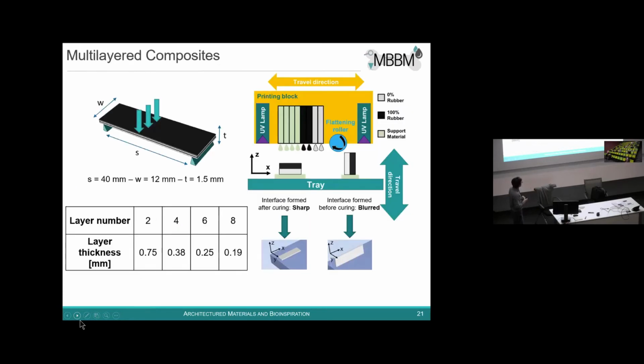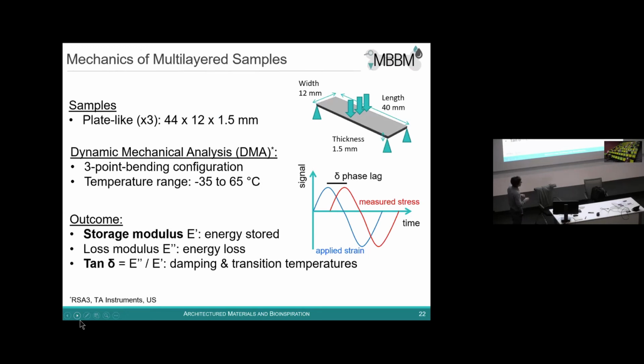And then we wanted to assess the impact of the interface on the behavior of very simple multi-layer composite materials. So we printed composite materials at the millimeter length scale of alternating layers of soft and hard polymers. And we printed them such that the interface between the different layers was sharp or was very broad. We printed these, and then we performed dynamic mechanical analysis to measure the dynamic properties.